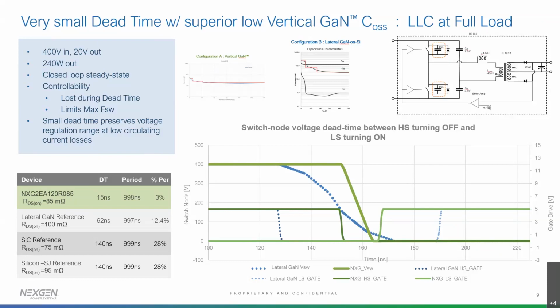And what you see, I should say the green solid lines are the vertical GaN FET, and the dotted lines are the lateral GaN FET. What you see is that on the basis of a 1 megahertz switching LLC device, we only need a dead time with a vertical GaN device of 15 nanoseconds between the switch turning off the high side and turning on the low side in order to maintain the zero voltage switching situation.